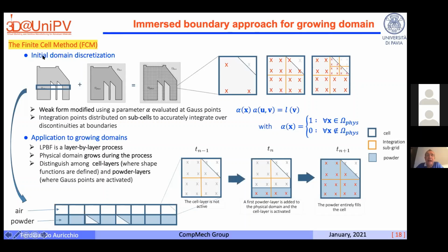In particular, we are going to look at the finite cell method, but besides that, we combine the classical finite cell method with another ingredient, because the dimension of the finite element that you introduce is not so small as to really describe the process of laying down, for example, powder, melting the powder and then describing the solidification process. So we also introduce Gauss integration refinement in order to describe the progressive deposition of layers. So we need to distinguish between the cell dimension, which is basically the dimension of the finite element mesh, and the powder layer dimensions. We really need to distinguish between the physical ingredients and the computational ingredients.